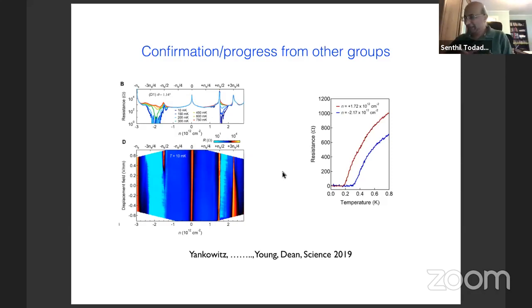So if you have a Dirac point, right? Suppose in some calculation you found a Dirac point. Now, your electron goes around the Dirac point in momentum space, you know that the Dirac spin rotates by 2 pi so that the Berry phase is pi. So this is the famous pi Berry phase for Dirac fermions, right? Now, so long as C2T is preserved, you can't change the pi Berry phase continuously to anything else, because C2T quantizes the Berry phase to be multiples of pi. So any perturbation that you add to the system, so long as it preserves C2T and is weak, will preserve the Dirac points. Is that good?